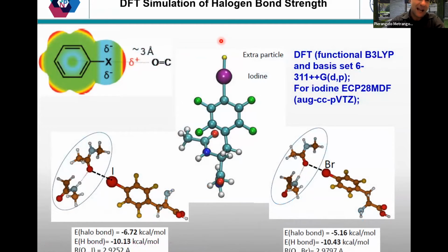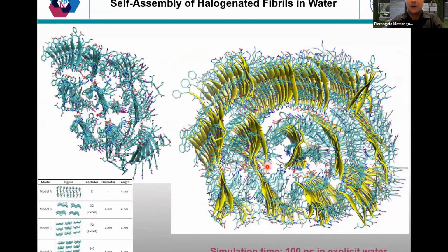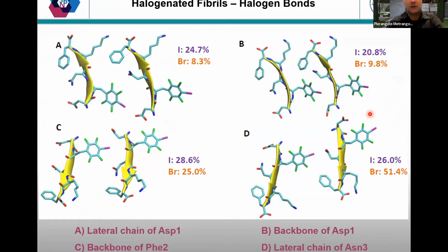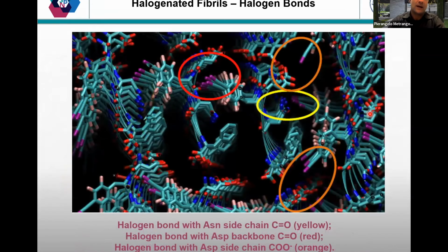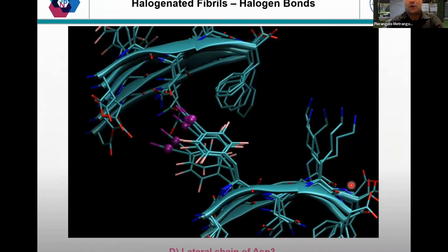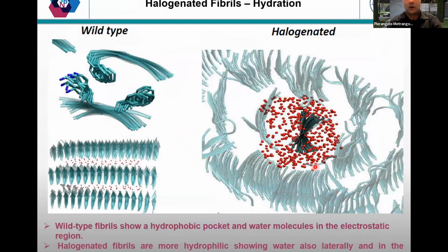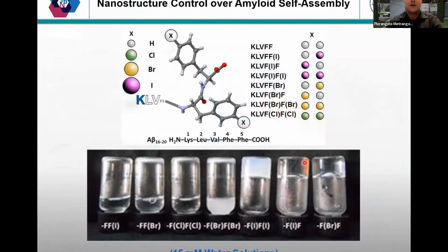So we calculated the sigma hole on top of the iodotetrafluorobenzene molecule and took that as an extra particle into the full fibril, which is made of 240 monomers. A lot of different possibilities arise for halogen bonding, where, for example, in the formerly hydrophobic pocket, now we have a fully open hydrophilic pocket where the iodotetrafluoro group is binding the oxygen of the aspartate and the asparagine. So, not surprisingly, this formerly hydrophobic pocket becomes polar and hydrophilic, and there are a lot of water molecules inside the pocket.